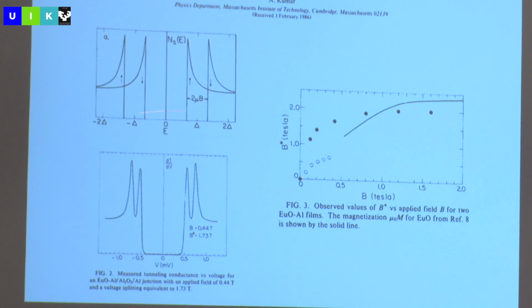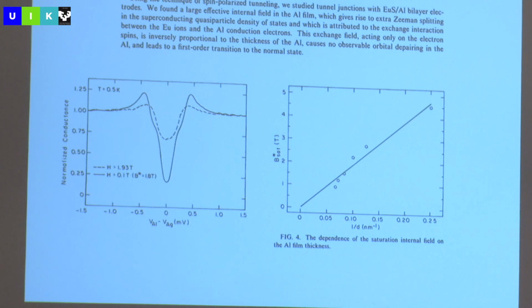And not only that, but the superconductor thought, based on this splitting, that it was in, depending on the external magnetic field applied, somewhere between 1 and 2 Tesla of external magnetic field, just from putting this material on top of it. So that does seem pretty enticing. And this field modernized itself. It was studied extensively by Tedrow and Meservey at MIT, and now taken over by Jagadeesh Moodera, also at MIT, of how, as a function of thickness of the film, the effective magnetic field would change. This is a 4 nanometer film, thicker, thicker, thicker, but as the aluminum film became very thin, this really felt like it was in a 4 Tesla magnetic field.